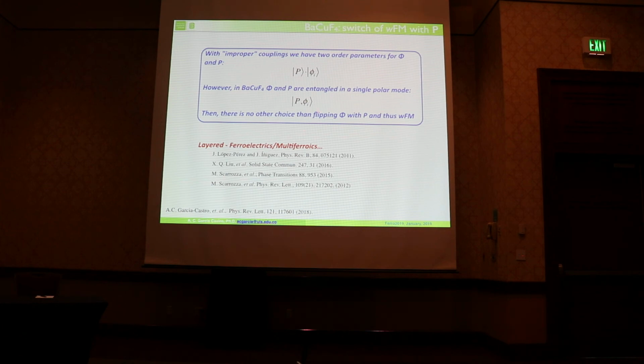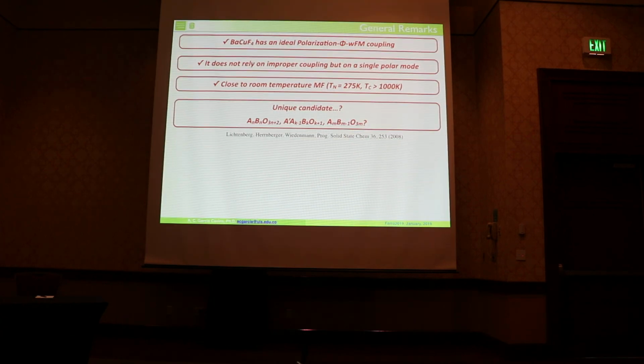And then there is no other choice than flipping the rotation when we flip the polarization. Okay? And in here there have been reported some layered ferroelectrics and possible multiferroics that we can look for. Okay? So as general remarks, we know that BaCuF4 has an ideal polarization and magnetization coupling. It doesn't require the improper coupling. Okay, so that's really interesting. It's already a close to room temperature multiferroic, in which the Néel temperature is close to 270 K, and the Curie temperature for the ferroelectric ordering is close to 1000 K.